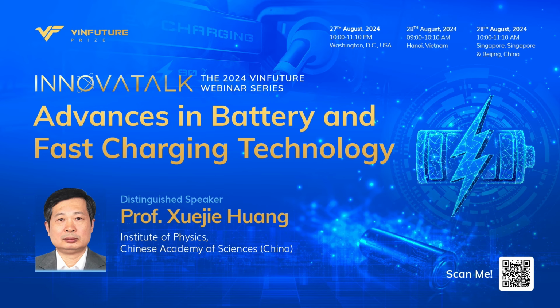We have not only a laboratory to do research, but we also have pilot factories in Sunshine Lake laboratory. So we can produce up to a few hundred kilograms of materials per batch. If you like, you can get our samples, for the nickel 90 and also the nickel 94 samples, to test the performance. You are also welcome to contact us. We have a laboratory not too far from Hong Kong. We can make not only NCM, but also good anode materials based on silicon and tin. We can also provide samples if you like.